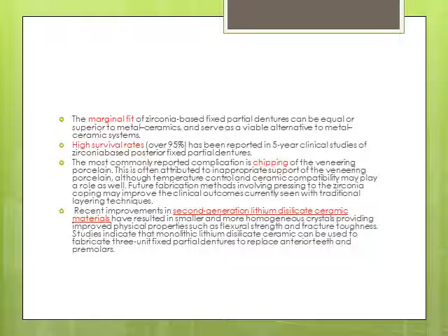The marginal fit of a zirconia-based fixed partial denture can be equal, as we said before, very good marginal fit compared to metal ceramics. The survival rate is very good. The most commonly reported complication is chipping of the veneering porcelain.